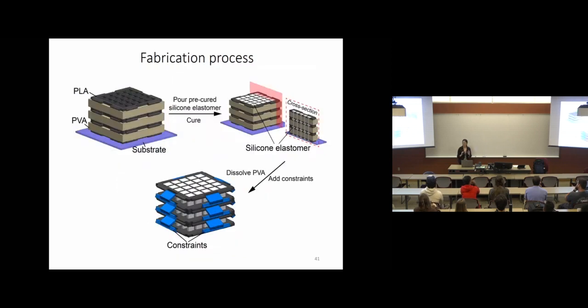With this idea in mind, we fabricate this energy-absorbing material. The main idea is that we form these multi-layer structures. In each layer, there is an array of wide columns. How do we fabricate them? We use 3D printing together with sacrificial molding. We first 3D print this structure composed of PLA and water-soluble PVA. Then we pour the pre-cured silicone elastomer and cure it. Then we dissolve the water-soluble PVA and eventually obtain this freestanding structure. Then we further add these hinges so that we can achieve the deformation mode we want. On the other hand, please also note that those wide beam structures are all internally connected, such that we don't have a high requirement of adhesion between different layers to ensure the deformation.